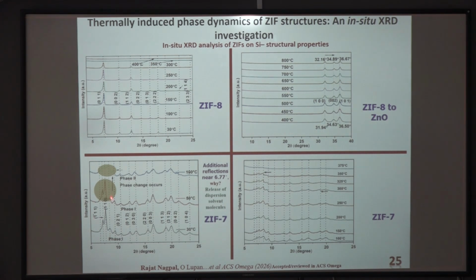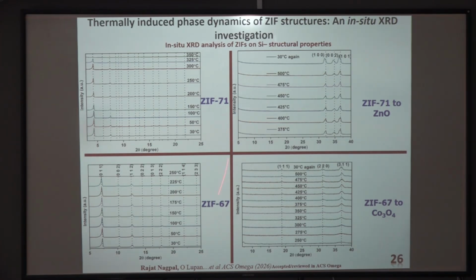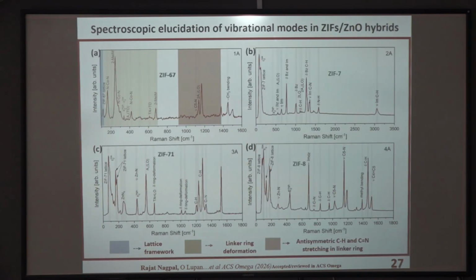And in ZIF7 case, here we can see going from 50 degrees Celsius to 100 degrees Celsius, additional reflections can be observed, which can be attributed to the release of dispersant solvent molecules, and at high temperatures we can see due to thermal stress there is a shift in XRD peaks. And among ZIF71 and ZIF67 particles, at a certain temperature their transformation into metal oxide and loss in crystallinity can be observed. For ZIF67, the central metal is cobalt, so its transformation into cobalt oxide can be observed, unlike the other cases.